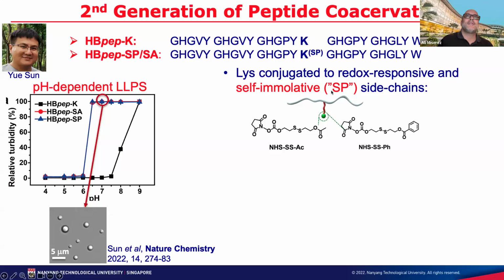If you don't have this modification, if you take the original peptide, what you see here is the turbidity, okay? If you have high turbidity, it means you have coacervation. If you're below here, you're in solution. So if you look at the original peptide called HB-PepK at pH 7.5 or 8 or something, there is no coacervation. But once you do the chemical modification, you see that at pH 6 or 7 here, you actually have this phase separation. So spontaneously you form this phase separation.